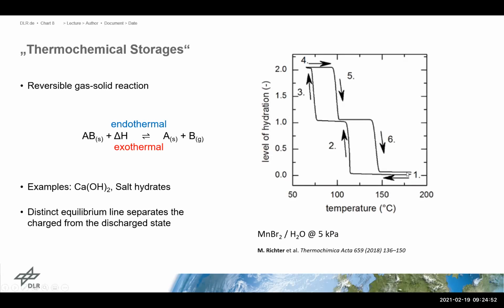We start at high temperature, position 1, we slowly reduce the temperature, and at a certain temperature, 130 degrees for instance, we see a clear step, an increase of the mass, which can be calculated to 1 mole of water, which is attached, reacted with the manganese bromide, actually. Then we reduce the temperature further, and we have a clear second step at something like 75 degrees Celsius. For the backward reaction, we increase the temperature, everything is the same, gas pressure is the same. We need something like 90 degrees Celsius to release the first mole of water, and then again 140 degrees Celsius to release the second mole of water.